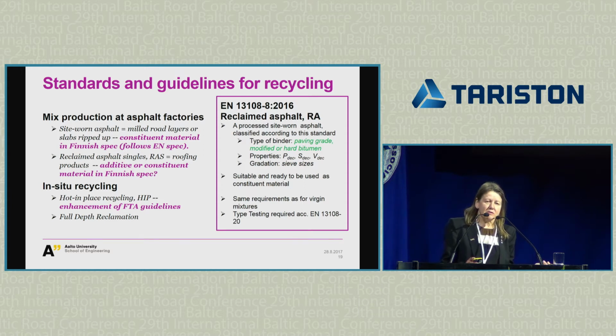One is the type of binder, if it's paving grade bitumen, modified or hard bitumen, then you have to declare penetration, softening point, soft bitumen's viscosity, gradation, of course. So for these shingles, the question is now, is it really an additive, or should it be treated like reclaimed asphalt as a constituent material? But the one thing in these recycled materials is that when you use them in the asphalt mix, for instance 50%, the mix has to meet the regular mix requirements, so type testing. And if you change something, you need to do a new type testing.